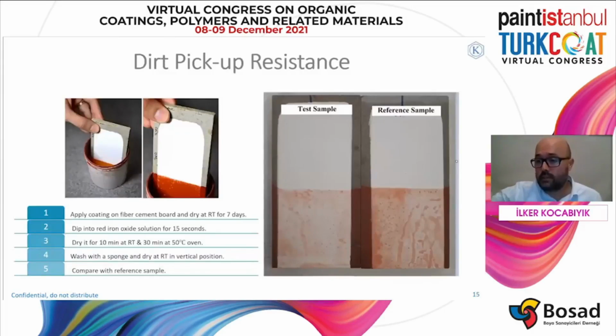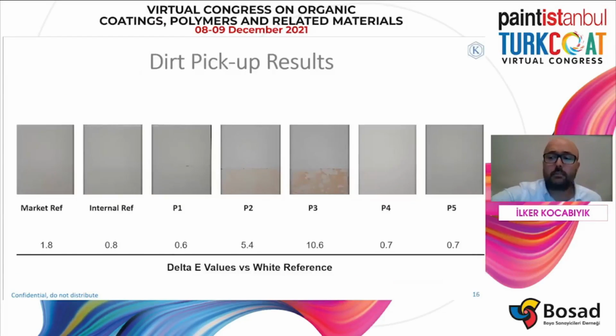Dirt pickup was tested in lab conditions by dipping the paint panels into an iron oxide red solution and evaluating after cleaning. Evaluation is made both visually and by measuring color difference with a spectrophotometer. Delta E values indicate color difference between the original white surface and the surface that is exposed to dirt. The lower the delta E value, the better the dirt pickup resistance. Best dirt pickup resistance was obtained with prototype 4, P5, with a delta E value of 0.7.